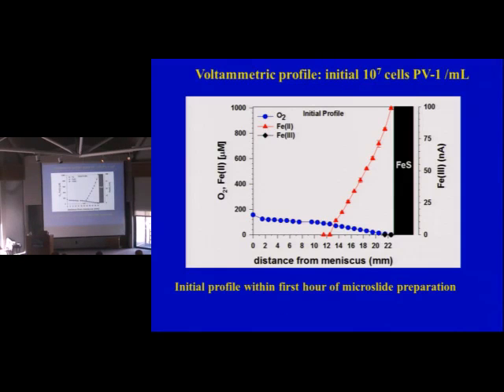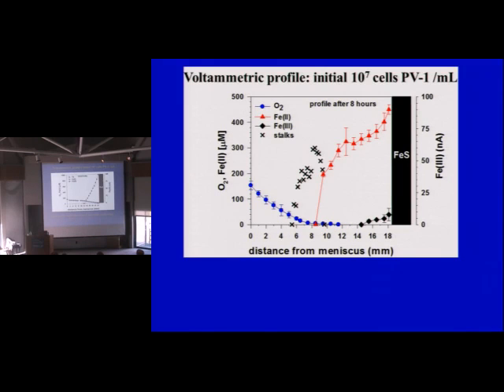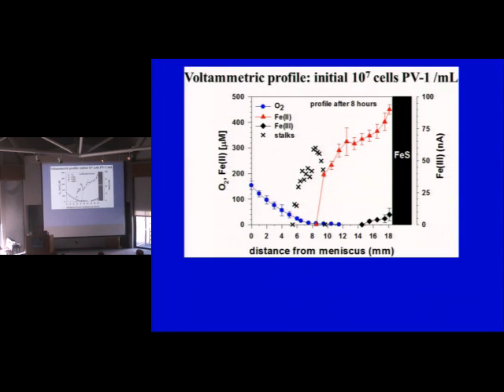So here's what a profile looks like when you're using like 10 to the 7 cells per milliliter. When you first set it up, it's going to take a while for everything to get to what you would call a steady state. And what happens is you see the oxygen content go down, and here's your iron going up, opposing gradients. What happens if you do it after about 8 hours? Now you see your oxygen going down very nicely in a gradient, much like you'd expect in a sediment or mat profile. Here's your iron. Notice a boom, it crashed really quickly.